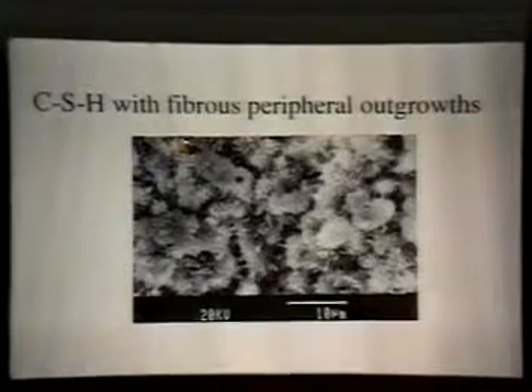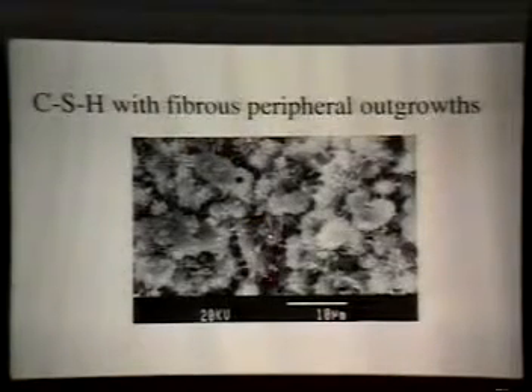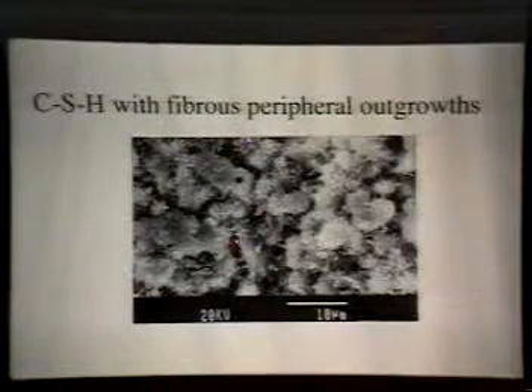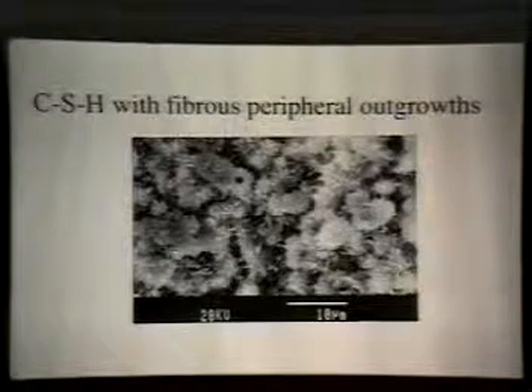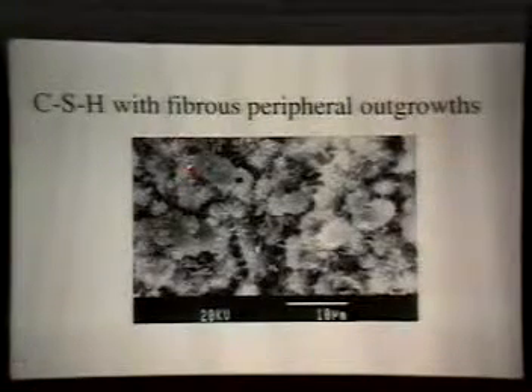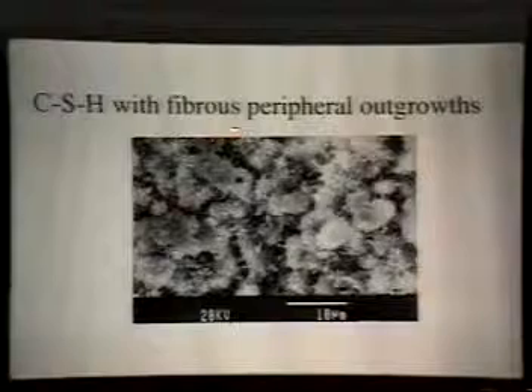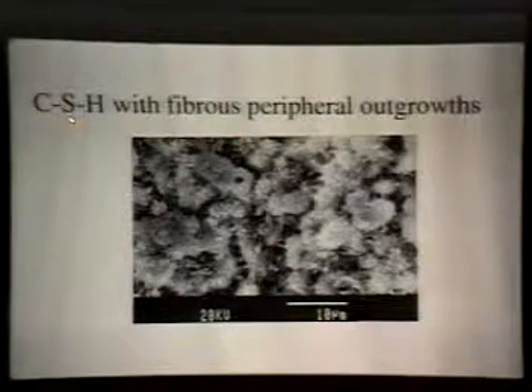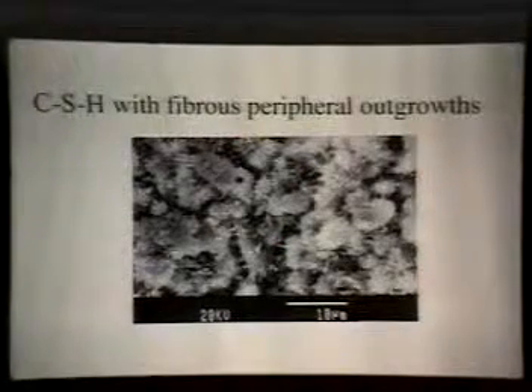As you can see, this is a very porous concrete. It's also permeable. You can see all the channels. So it's basically a high water-cement ratio concrete. But this is your principal binder material of concrete, calcium silicate hydrate.